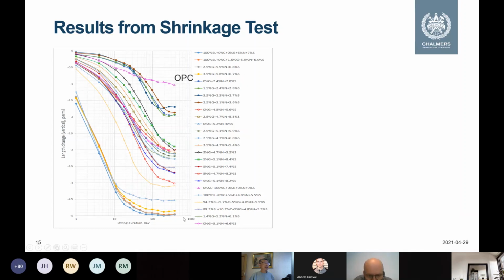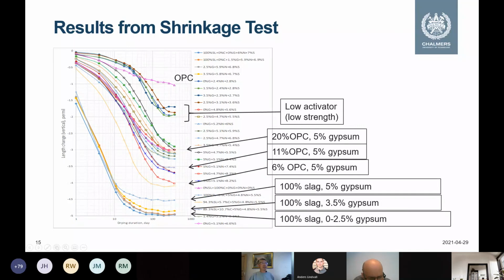But if we add gypsum into the alkali-activated slag, it will decrease the shrinkage. If we add cement into the alkali-activated slag, we will decrease the shrinkage even more. Here, in this range, I think I have some pictures. You can see that this is by adding gypsum. This is by adding Portland cement. So we reduce the shrinkage. And if we consider both Portland cement and gypsum, we can significantly reduce the shrinkage from 5 per mil to 3 per mil in this range.